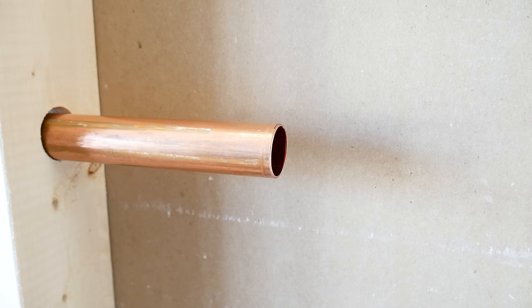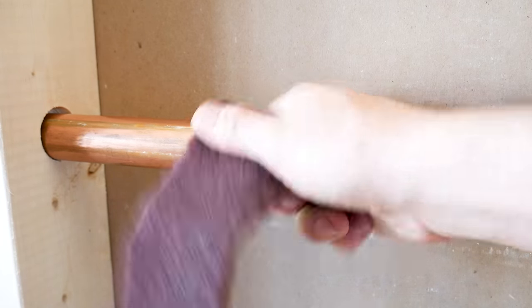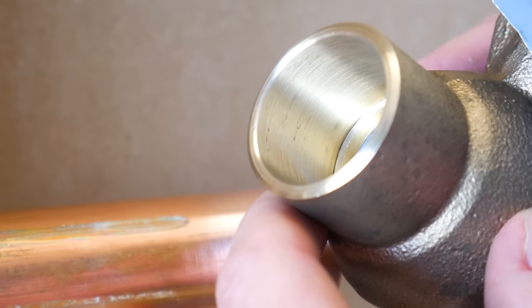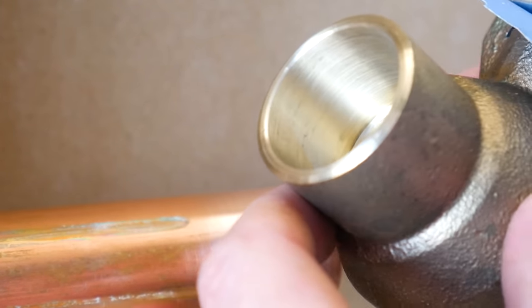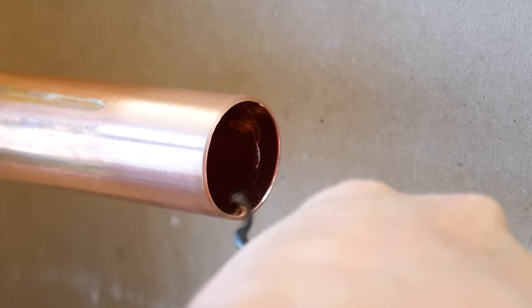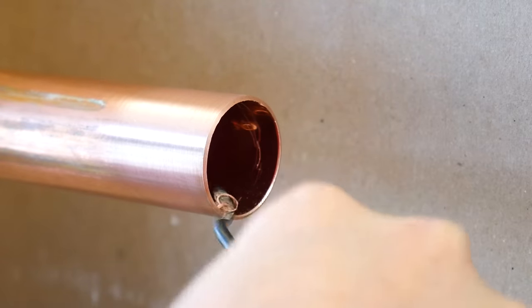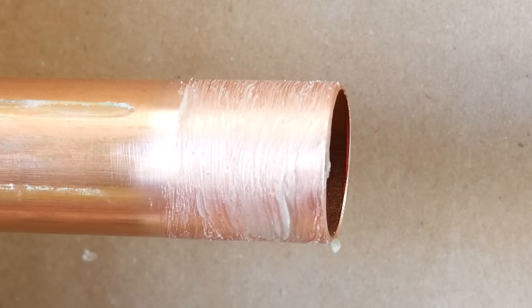So here we go. Just as you normally would, clean the pipe and fitting real good using either some sand cloth or an abrasive pad like this. Then, you want to deburr the inside of the pipe using one of these or a pencil reamer like this little guy right here. After, you can apply your flux, making sure to cover the pipe properly, and start heating